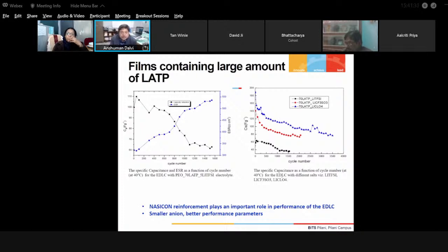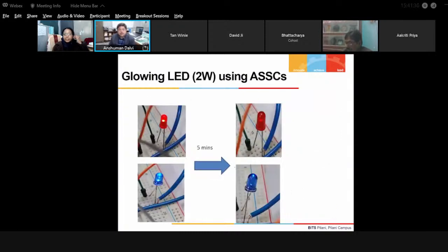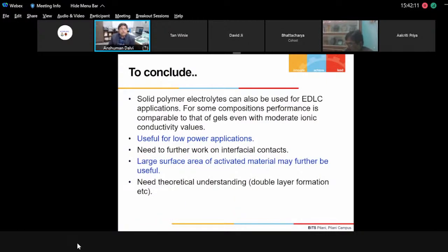And this is appreciable also with respect to the fact that one can use it for glowing the LEDs. Say a 2 watt LED with an all solid state supercapacitor, different LEDs could be glown, and up to 5 minutes of constant discharge we have seen for white, red and blue LED. And of course you have to make a combination so that the total voltage is more than 2 volts. So one of the cells can provide 2 volts of voltage here. So this is indeed a supercapacitor, and in the solid state it works quite well.